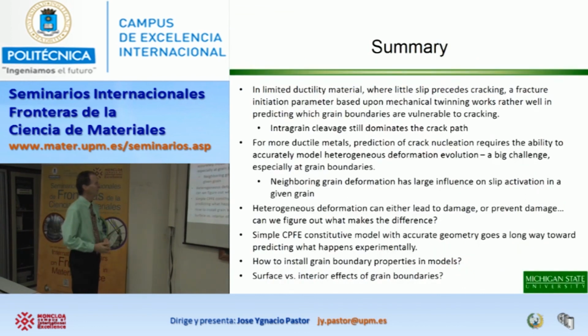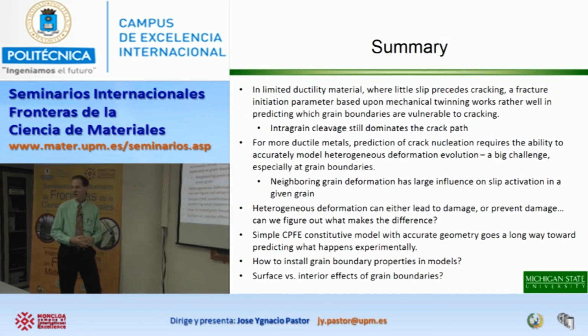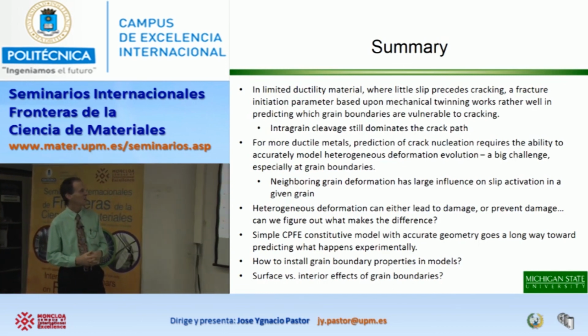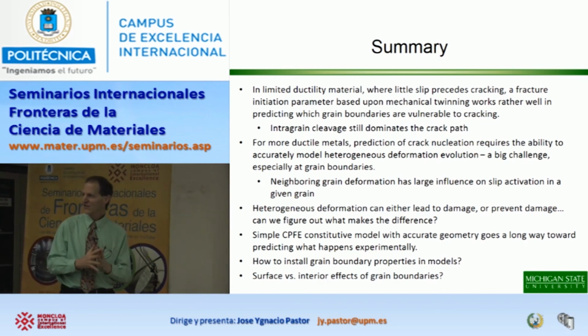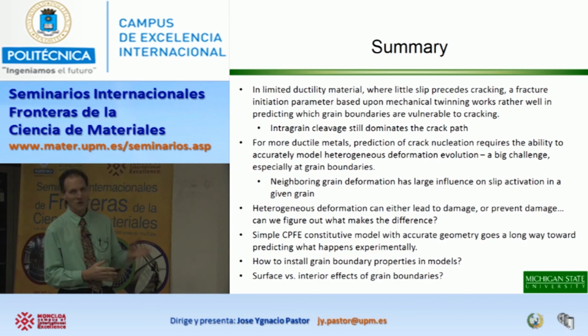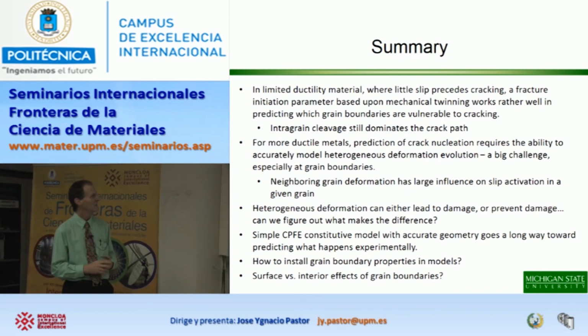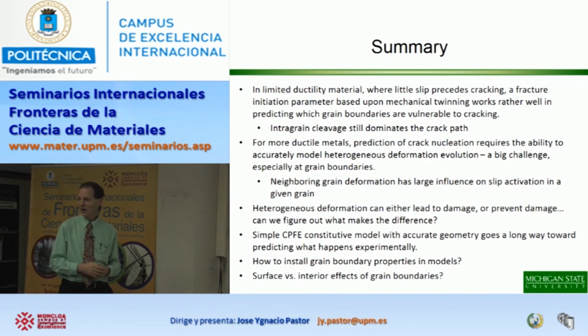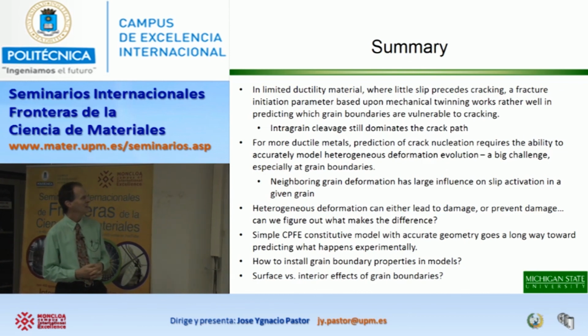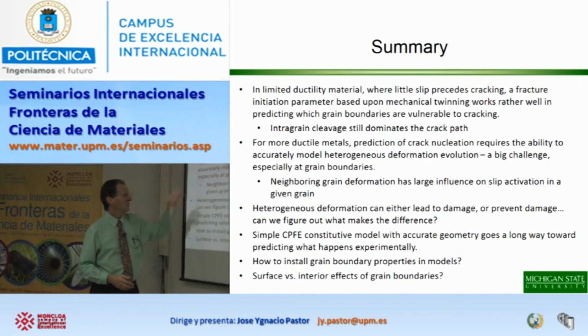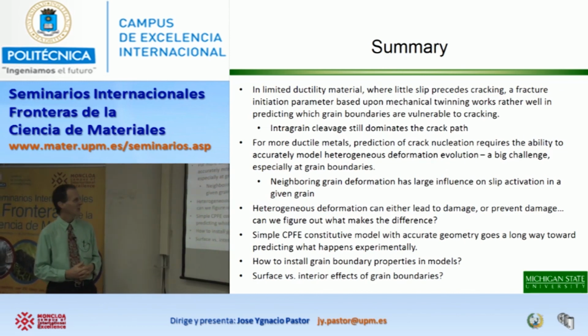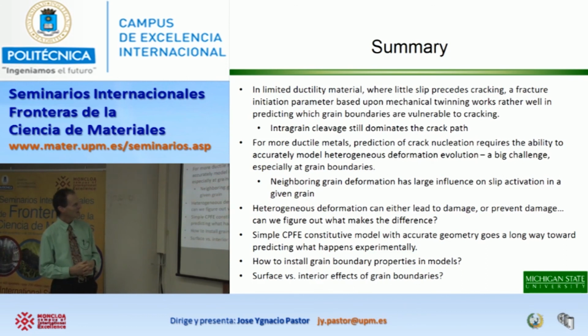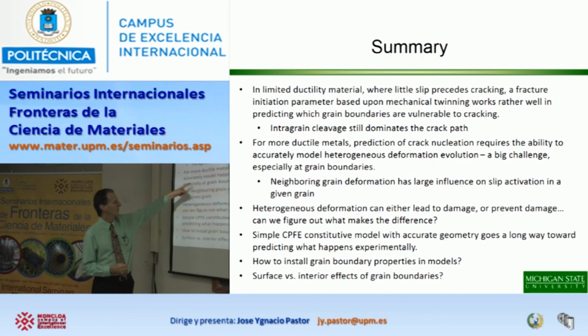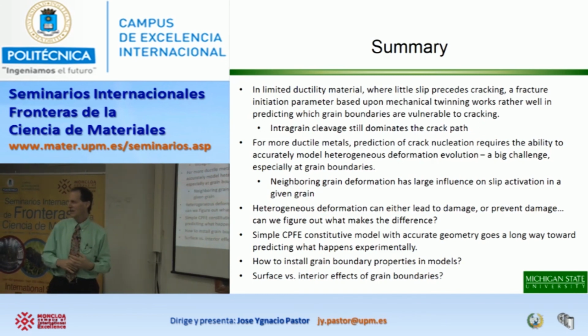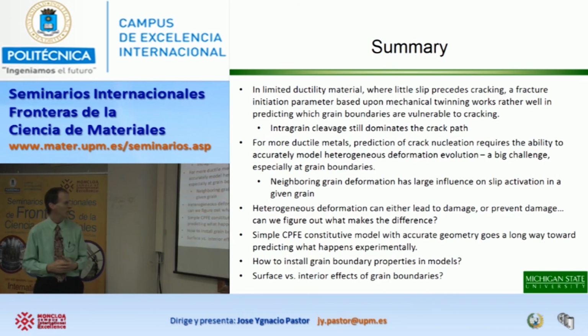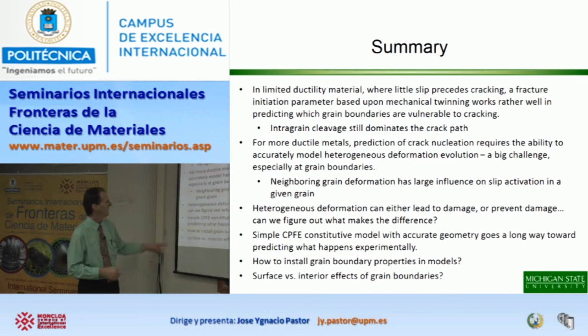So with that, I'll summarize. Basically, with a limited ductility metal, such as titanium aluminide, where just a little bit of slip occurs before cracks happen, we could develop a fracture initiation parameter that did a decent job of predicting which boundaries are more vulnerable to cracking than others. But even in that case, cleavage still dominates the crack process, but the grain boundary has some influence on that. But for more ductile metals, the prediction of a crack nucleation requires the ability to really effectively predict the heterogeneous deformation that takes place, especially near grain boundaries. And that's a big challenge.